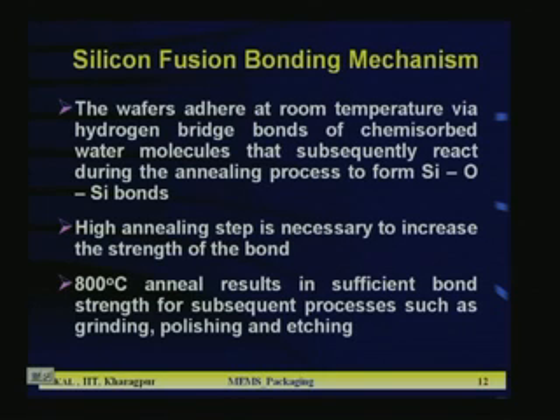A high annealing step is necessary here to increase the strength of the bond. An 800 degrees C anneal results in sufficient bond strength for subsequent processes such as grinding, polishing, and etching. Now, in many cases of MEMS devices, you need polishing of the wafers as well as grinding of the wafer. That means you are going for some mechanical agitation. Your total structure will face certain mechanical agitation, and because of that you need a very good and strong bonding strength. So, for that you need to treat the complete bonded wafer at a very high temperature, that is known as a high temperature thermal anneal, and it is normally more than 800 degrees C.